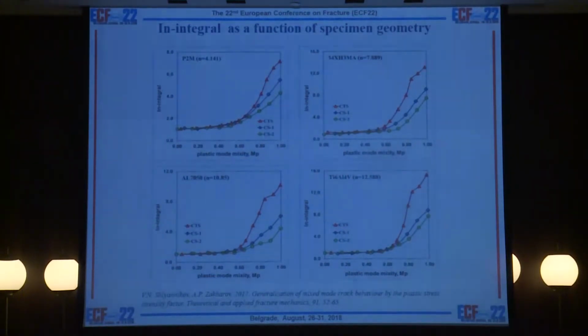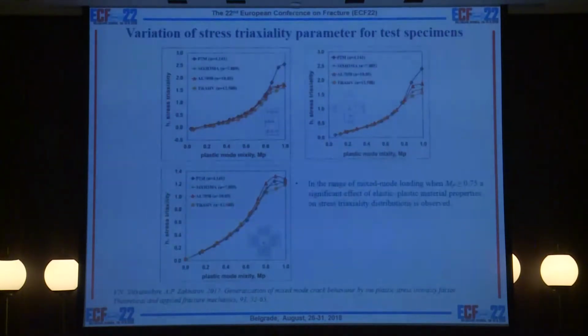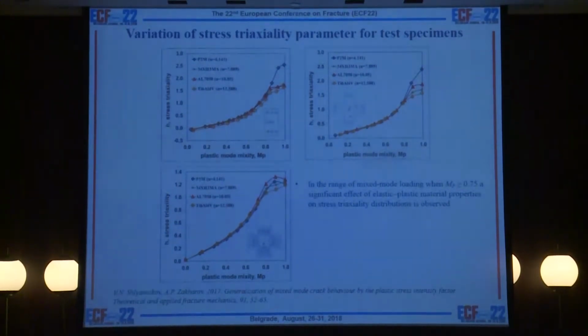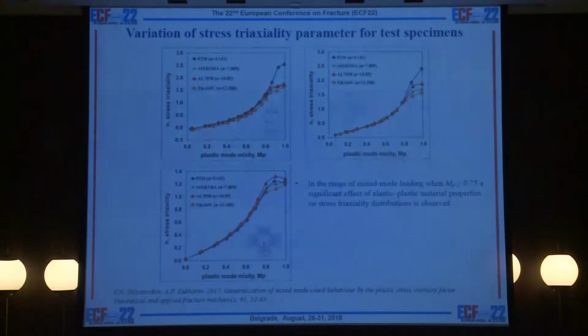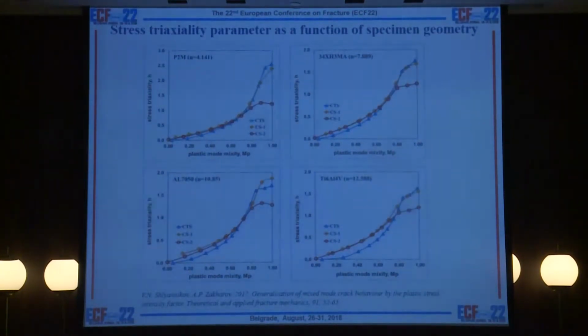In this figure, you can see the IN integral distribution as a function of specimen geometry. Again, I would like to pay your attention that the influence of specimen geometry, the constraint effect, is realized when the MP is higher than 0.6. And then in the next figure, you can see the distribution of the stress triaxiality parameter. Again, a significant effect of elastic plastic material properties is observed when the mixed mode mixity parameter MP is higher than 0.75. In this figure, you can see the distributions of the stress triaxiality parameter as a function of specimen geometry.